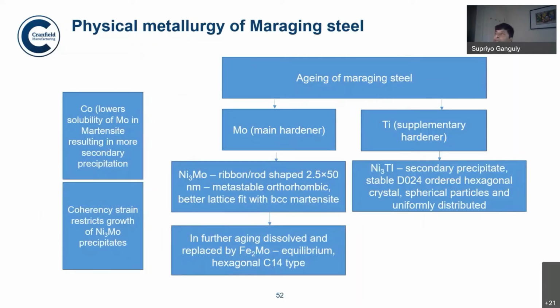Just a little bit about this alloy. Molybdenum is the main hardener, and it hardens the matrix through formation of a Ni3Mo kind of structure, whereas titanium is a secondary hardener. It also forms Ni3Ti in this, and in further aging, Ni3Mo is dissolved and Fe2Mo also forms, which adds to the strengthening behavior. Cobalt is alloyed mainly to lower the solubility of molybdenum in martensite so that it can age efficiently, and the coherency strain of this type of alloy restricts the growth of Ni3Mo type precipitate.